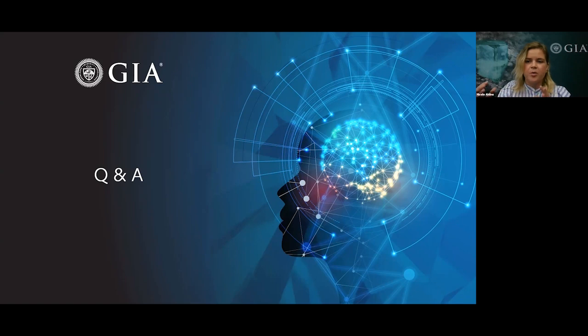And so after that corundum was done growing, it's still in the ground, so it's still at higher temperature, higher pressure than at the ground level. I'm sorry, after it reached the surface and is plucked from the ground, that titanium oxide is exsolving out of that corundum, and it's being created into silk. So there are different paths that titanium oxide, in that form of silk and that crystal, can form, creating different inclusions within your sapphire and ruby.